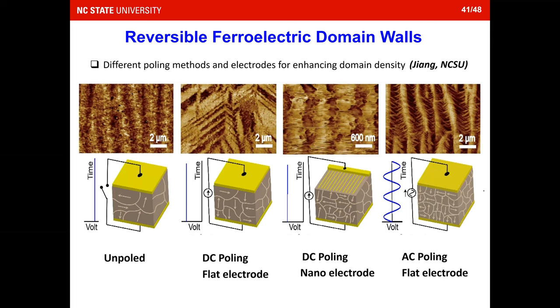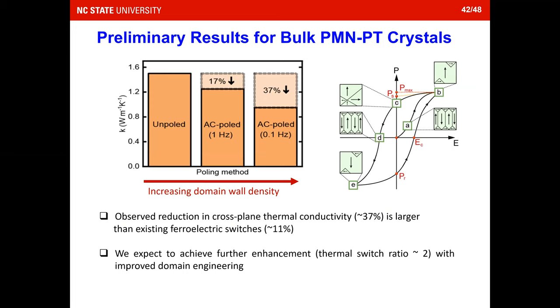If you don't pole these materials, you have random distributions of different polarizations. Then when you have DC or AC poling, or flat electrodes or nano electrodes, you can control the densities of the domains. Sometimes you can very nicely enhance the domain densities. And because you have control of these densities, the resistance at the walls will create lower thermal conductivity for the entire material. We did some preliminary studies on this type of material without all this fancy poling, but just a few data already showed that your thermal conductivity can be reduced by AC poling.